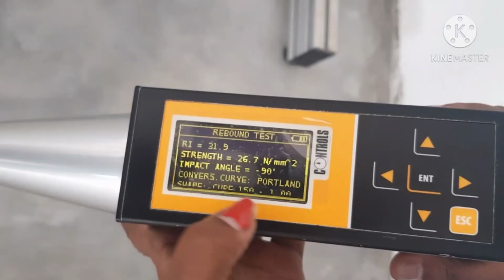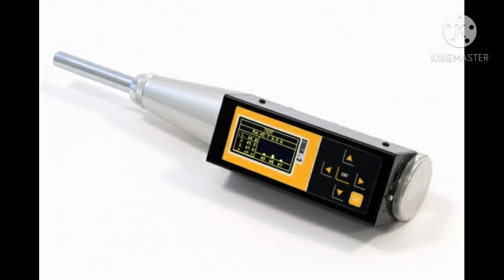In general, the rebound number increases as the strength increases and is also affected by a number of parameters, for example, type of cement, surface condition, moisture content of the concrete, age of concrete, carbonation of concrete surfaces, and so on. The advantages of the rebound hammer test are that the apparatus is easy to use and the equipment is inexpensive. The disadvantages of this test are that the results obtained are based on a local point. The test results are not directly related to the strength and the deformation property of the surface. The plunger and spring arrangement will require regular cleaning and maintenance. Flaws cannot be detected with accuracy.